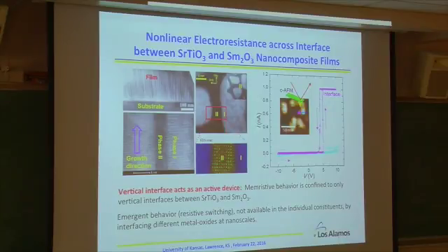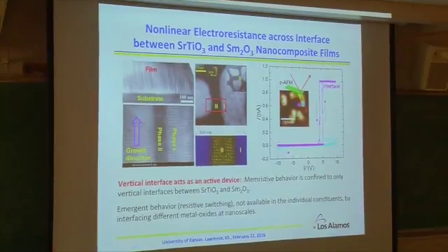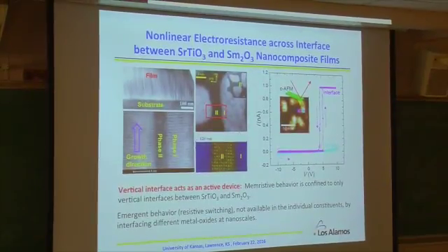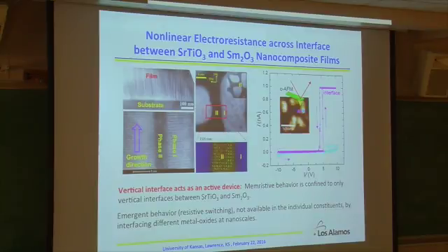So for example, strontium titanate is transparent. You receive this single crystal, clear, transparent. You put it in a vacuum, you heat it up, and then you see the color change to yellowish. If you heat up to an even higher temperature, you can change that to black color. Okay? So basically it's just strontium titanate, you don't have oxygen at all. So it makes it very conductive.